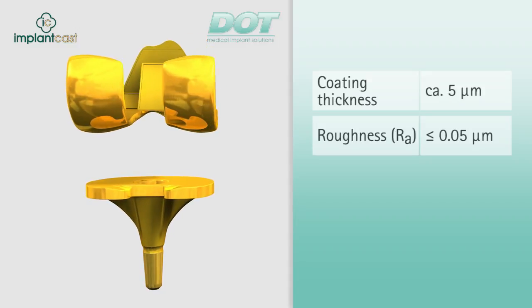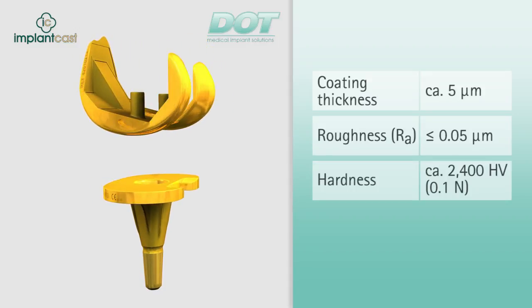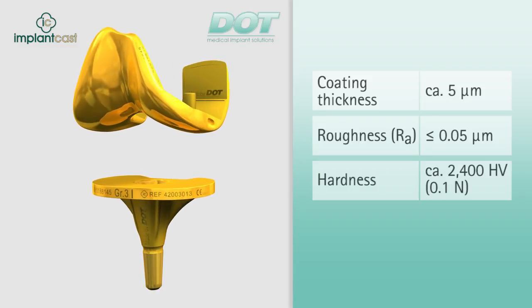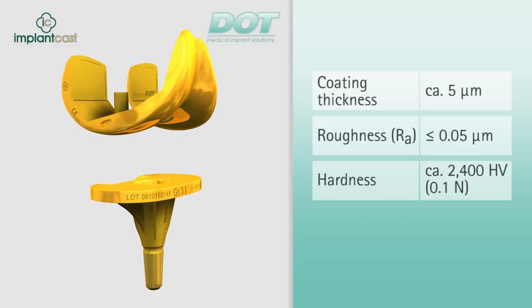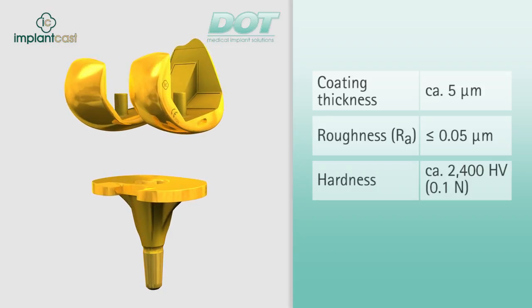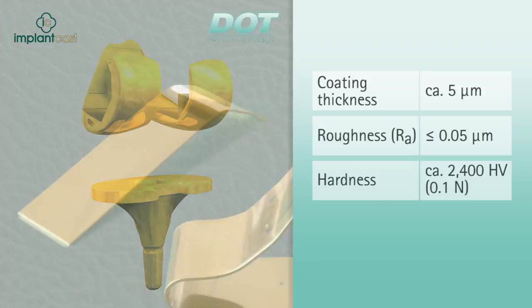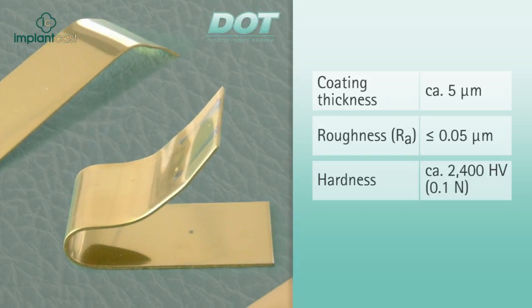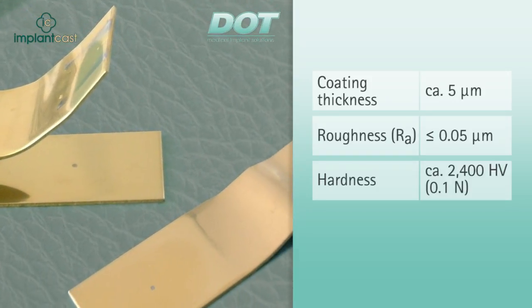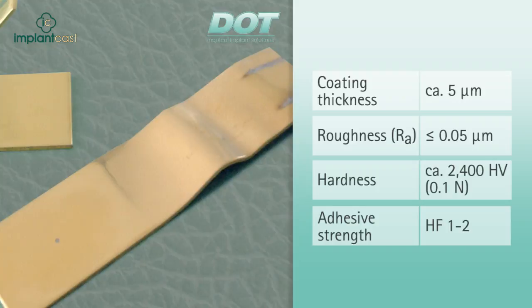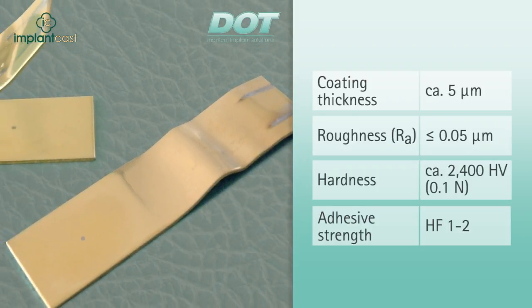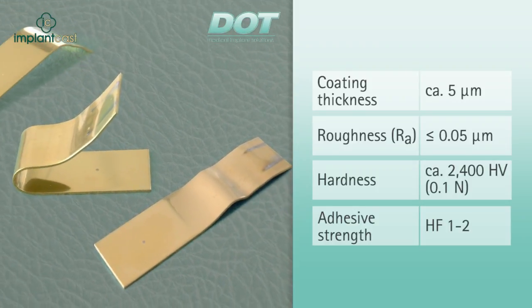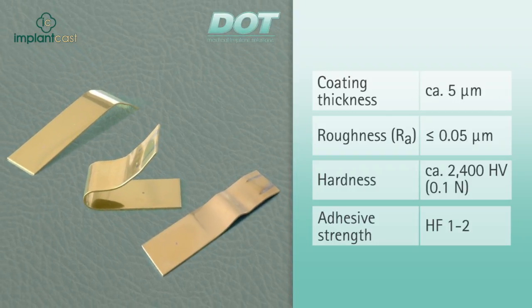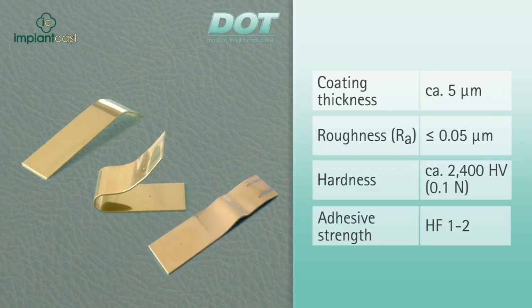The hardness of the titanium nitride layer is approximately 2,400 HV, well above the results measured for conventional cobalt chromium molybdenum alloys. The most important parameter of the titanium nitride layer is the adhesive strength, which has been verified in various qualitative tests. These include the Rockwell impression test and mandrel bending test. Both testing methods showed that the titanium nitride layer exhibited very good adhesive strength.